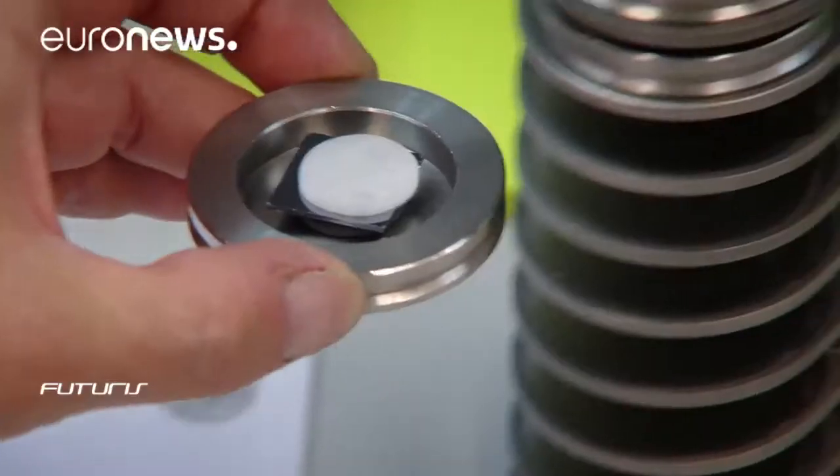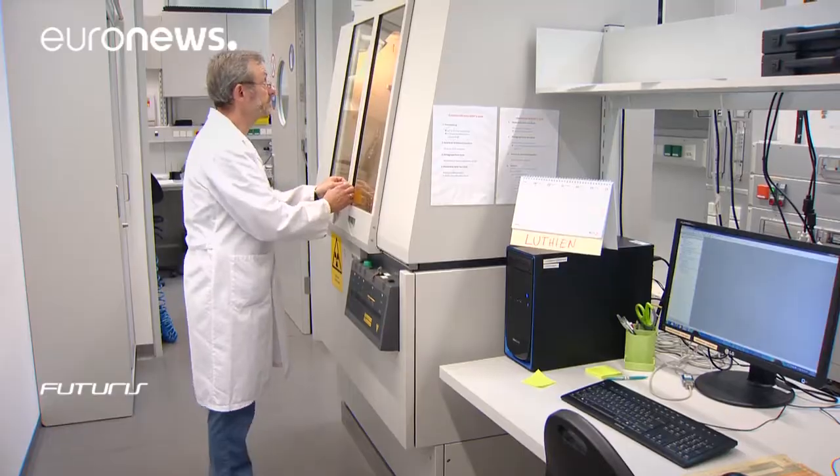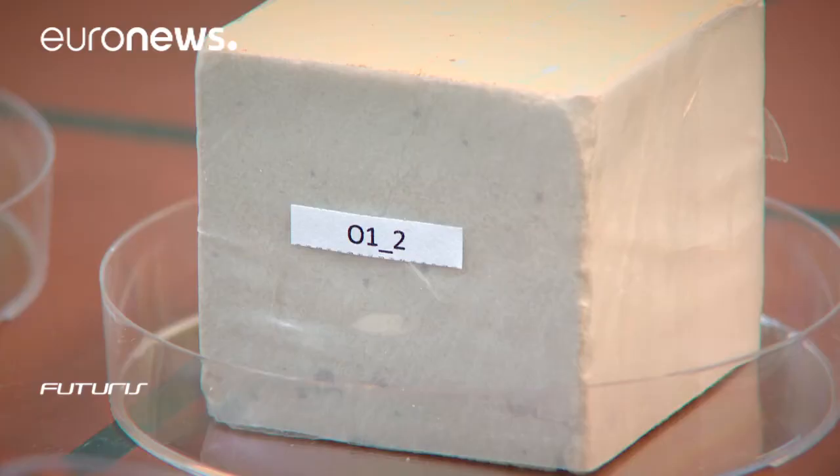We tried different things. We tried freeze-thaw, salts and acids, and we decided to go with thermal aging. So what happens is that we heat the stone, and at certain temperatures the minerals expand in certain directions, and when they expand they build up stresses to the neighboring minerals, and then they crack. And we need those cracks in order to consolidate them.